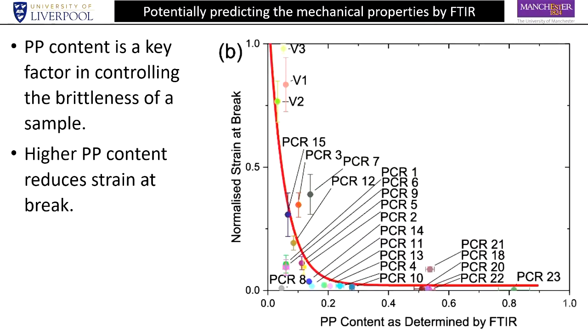The other key thing we've shown, and this is very widely known, but when you read papers and look into the scientific literature on this, it isn't often robustly shown in a large data set. Our bottom axis is polypropylene content, so more polypropylene, less polypropylene, and on this axis is strain at break. And essentially what you can see here is our virgin samples, which have no polypropylene, have a very high strain at break, and as soon as you have polypropylene contamination, you drop off mechanical properties dramatically. And this is, again, some of the things we've heard about in previous talks about the importance of being able to separate your polyolefins, which really allows you to generate a product with much higher value.